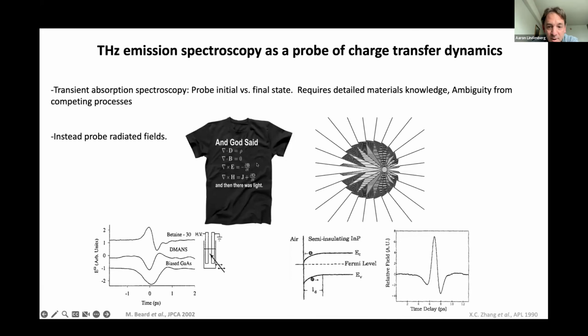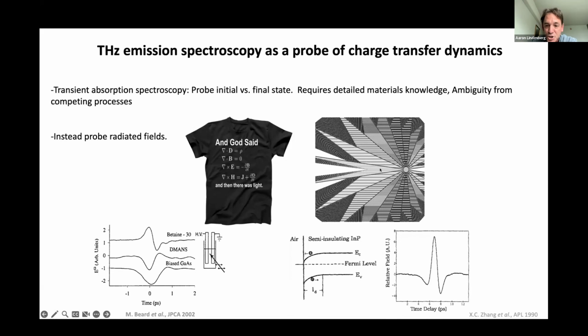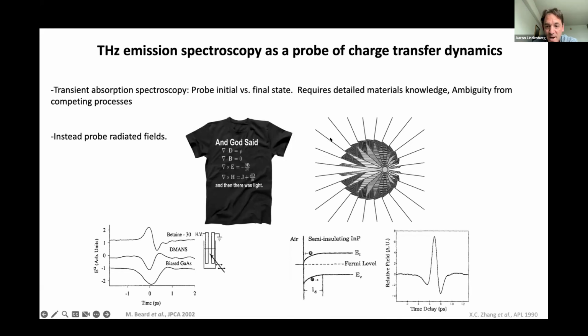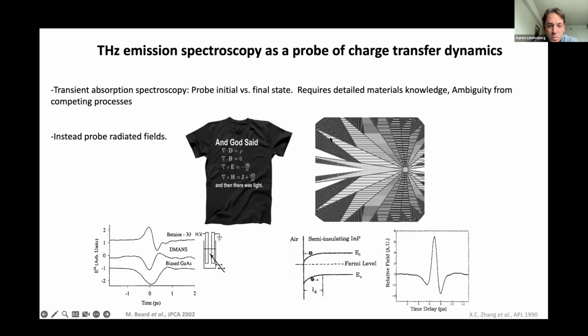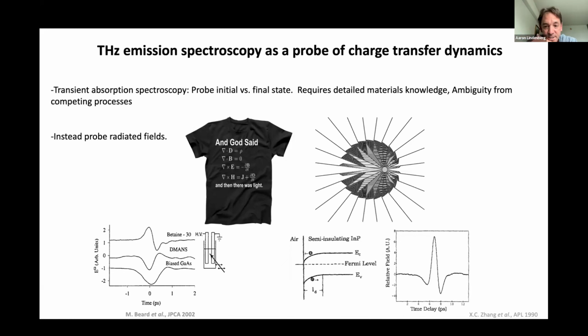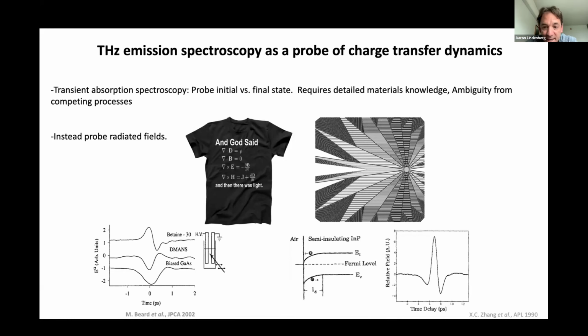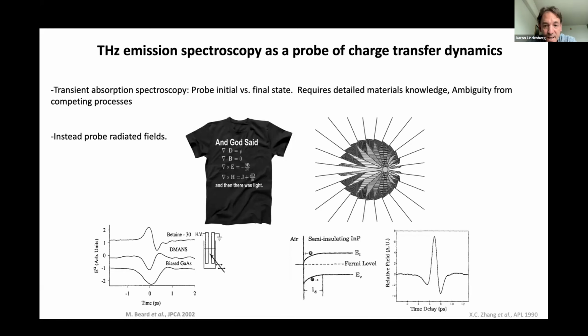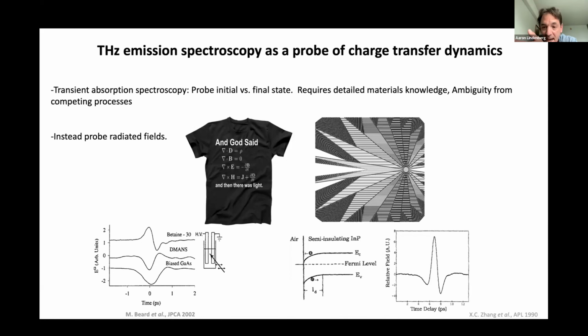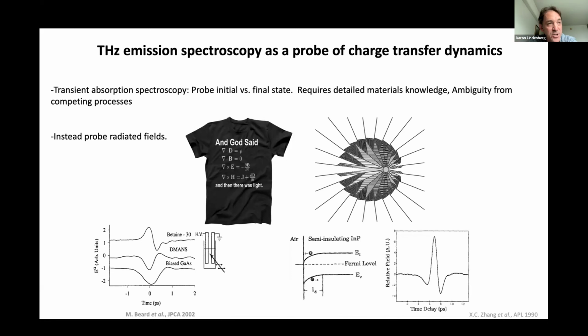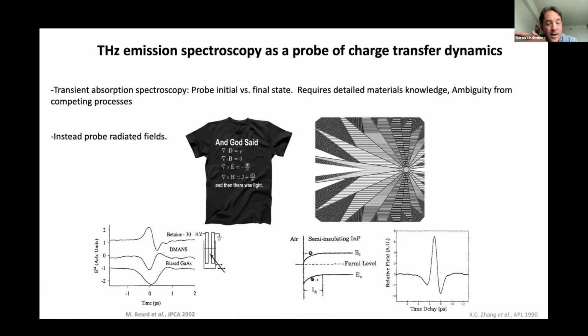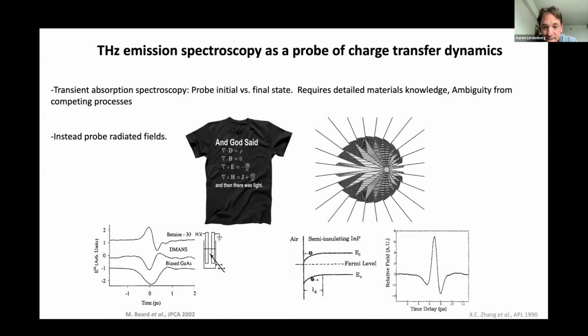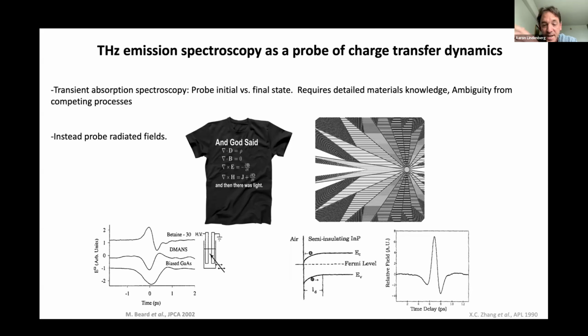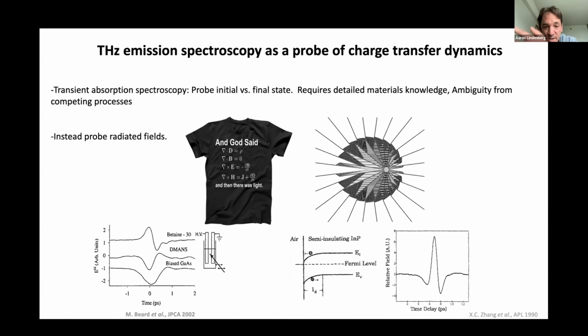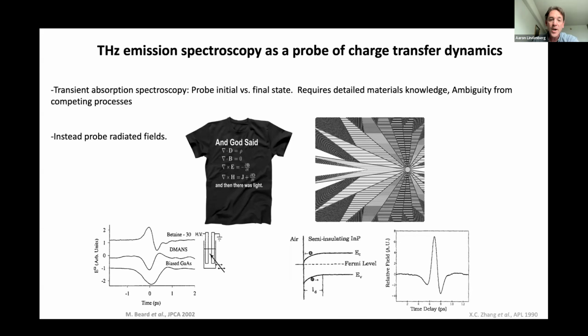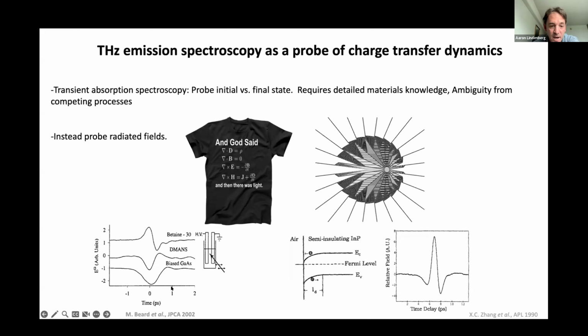We all know directly from Maxwell's equations that when you have an accelerated charge, the ordinary radial Coulomb fields falling off as 1 over r squared get turned into a 1 over r scaling, which gives rise to a radiated electromagnetic field. If the dynamics of this charge transfer process are happening on picosecond or sub-picosecond timescales, this is going to give rise to radiation at the inverse of that, at terahertz frequencies. Okay, so this idea is again not a new one.